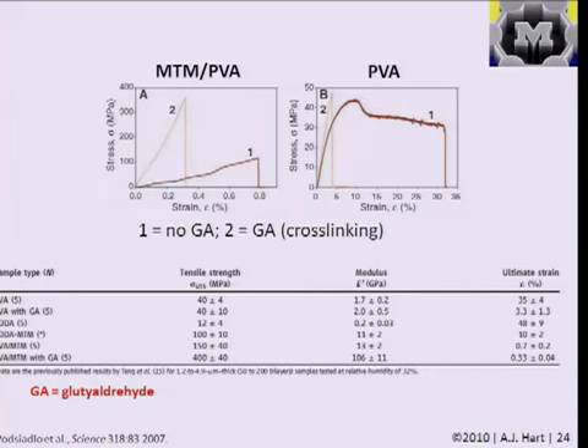And in case number 2, they add another species, GA, which stands for glutaraldehyde, which they find promotes cross-linking between the polymer and the clay, and the strength goes up by about a factor of 3. So by engineering this interaction between the polymer and the clay and architecting this nanoscale composite, they achieved about a 10-fold increase in the strength of the material.